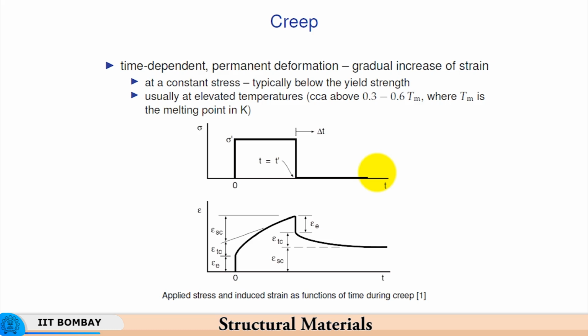Still it is not enough to design a pressure vessel based on these two considerations. One has to look at the creep related issues also, because even if the material is below the yield strength during operation, since it is working at a high temperature for prolonged periods of time, it can still undergo a significant amount of creep strain. What is significant depends upon how much strain would be permissible, how much strain would not interfere adversely with the functioning of that high temperature pressure vessel or equipment, which is something that one has to decide. So, we look at the mechanical behavior of the material under creep conditions.